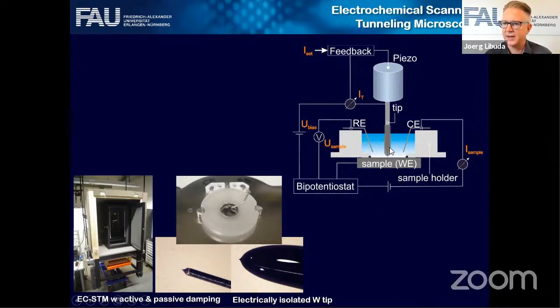And of course, there's one issue. You have to apply a potential to the tip. So the tip is also an electrode, and you will have currents between the tip and the other electrodes. So in order to minimize these electrochemical currents, the tip is typically electrically isolated, and you leave out only the very end of the tip. So that's how this experiment is done.